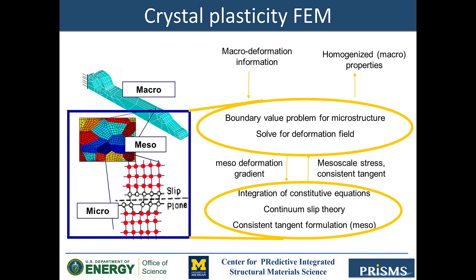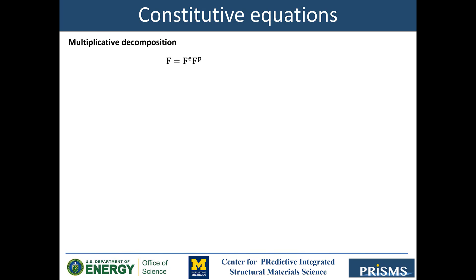In the Crystal Plasticity Finite Element method, the finite element solver handles the equilibrium of forces and the compatibility of displacements, while the crystal plasticity model captures the constitutive model at each integration point. In each iteration, the displacement field is captured by the FE solver, which generates the input deformation gradient tensor for the crystal plasticity model. The crystal plasticity model then generates the updated stress and algorithmic tangent modulus and passes it back to the FE solver to move forward to the next iteration. Crystal plasticity models are the heart of the CPFE framework.